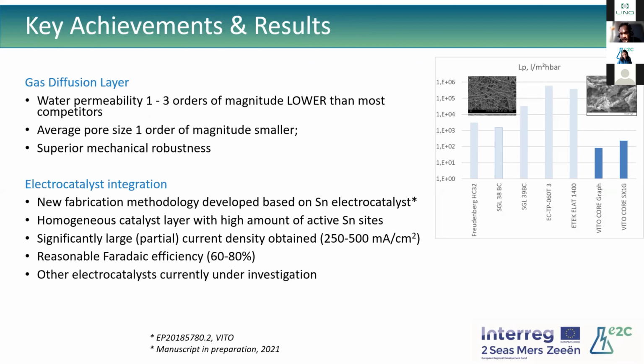So some key achievements and results. First, on the gas diffusion layer itself, without any catalyst, we make some gas diffusion layers ourselves. We tested them, characterized them, mainly the water permeability, the pore size, and the mechanical robustness. We compared with commercial gas diffusion layers, and compared to those, we had quite better performance, I would say, in the sense of lower water permeability and smaller pore sizes. Of course, that's not everything, because this is still without any catalyst.